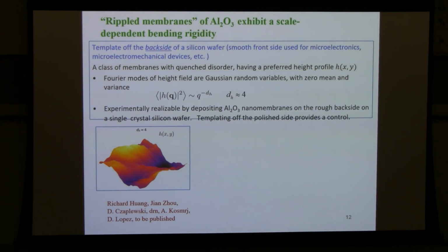And it's not quite the same problem because there's quenched randomness in the ripples in the plastic thing that I was passing around. I hope to get that back at the end. There's quenched randomness, but the quenched randomness has this interesting power law form that's somewhat reminiscent because this exponent is very close to 4. It's just a measured rippling of the backside. The front side has some roughness, but it's down by 3 orders of magnitude. The polished mirror-like side is very smooth. So that's going to be a control.